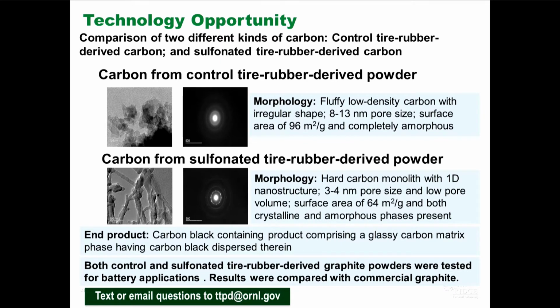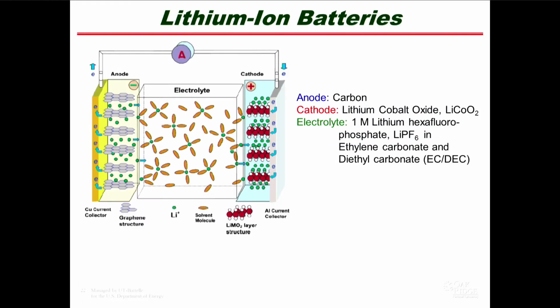Before we get into the results, let's see what a lithium-ion battery is. This is a schematic of a secondary ion battery. We have two solid electrodes, the anode and the cathode. Anodes are typically graphite, and the cathodes are lithium containing oxides like lithium cobalt oxide, lithium manganese nickel oxide, or lithium iron phosphate. The electrolyte is a liquid electrolyte, with 1 molar lithium hexafluorophosphate dissolved in ethylene carbonate and diethyl carbonate solution.